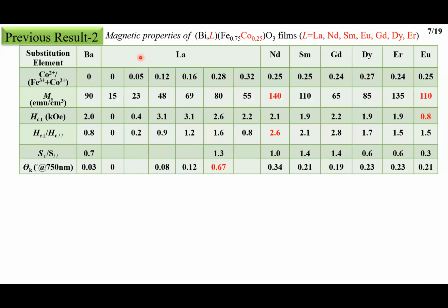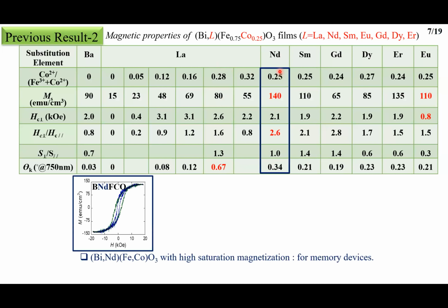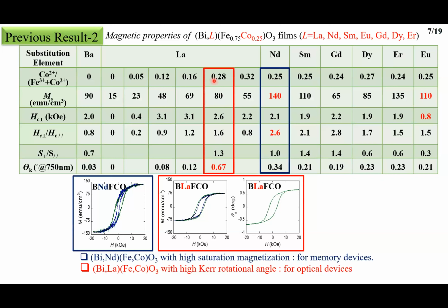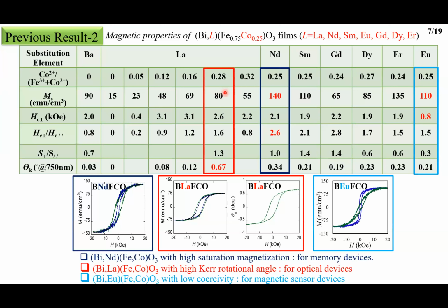So after that, I substituted many lanthanoids in the A site with cobalt concentration in the B site, and I could achieve, in the case of neodymium substituted bismuth ferrite, very high saturation magnetization and very high perpendicular magnetic anisotropy. So this material is better for the memory device application. In the case of lanthanum substituted bismuth ferrite, I could observe a very high Kerr rotation angle and of course very good saturation magnetization. So this is better for optical device applications. In the case of europium substituted bismuth ferrite, the coercivity is so low and the magnetization is so high, so I can use this material for magnetic sensor devices. By playing with many elements, finally I could come up with three important materials for device applications.